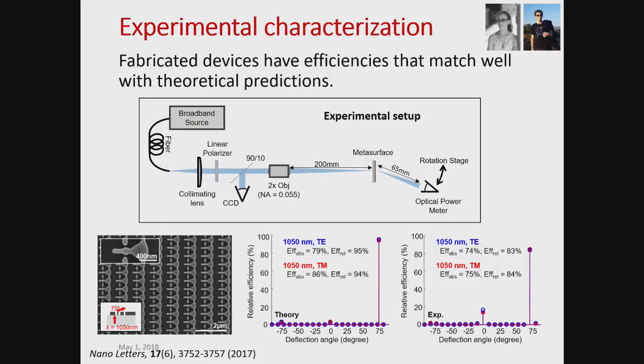Now, at the end, we are experimentalists, and we wanted to see if we can actually experimentally realize these devices. So what we did was we grew polycrystal silicon on an amorphous oxide substrate. We did conventional E-beam lithography and RIE etching to produce these type of structures, and we measured the deflection as a function of angle by this very simple setup where we weakly focus light and then mount an optical power meter on a rotation stage. What we see here, theoretically, is that we have relative efficiencies that are in the 90% range and absolute efficiencies around 80%.